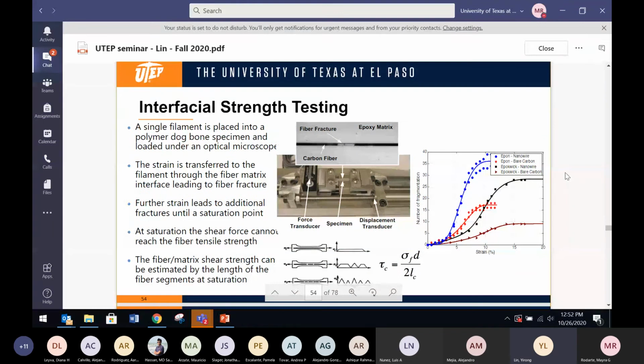Okay, so the first thing we characterize is to see whether it works or not, right? We just want to bring your attention to the blue and the red lines here, right? The blue line is with the nanowire interface, the red line is without. You see the number of fragmentations inside this fiber is more. The take-home message is that more fragmentations means more loading is being transferred from the matrix to the fiber. So that means with nanowires it is way better, right? So that's good. Next slide.